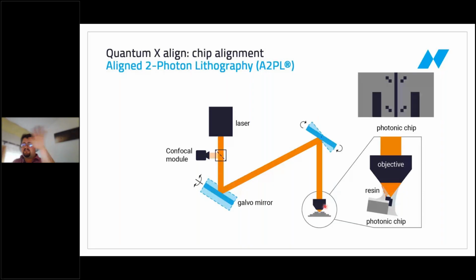And this allows us to scan the surface in the exact same coordinate system as we're using for the lithography. So there's no coordinate system mismatch that could enter here. And we use this to detect three, for example, but this would be the optimal number, three markers, three features that are on the surface of the chip or anywhere on or near to the chip. And then if you have three positions in X, Y, and Z, because the confocal can also detect the correct height, now we can, with the 3 points, we can get the perfect alignment, position, and rotation and tilt.